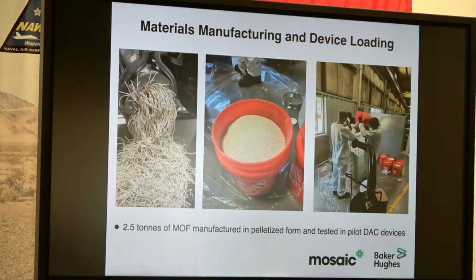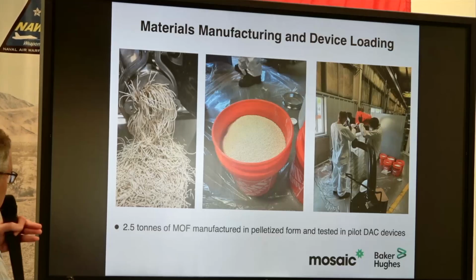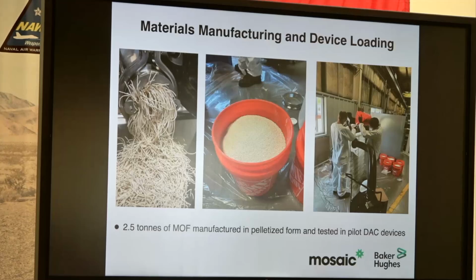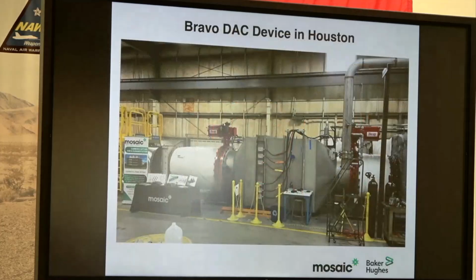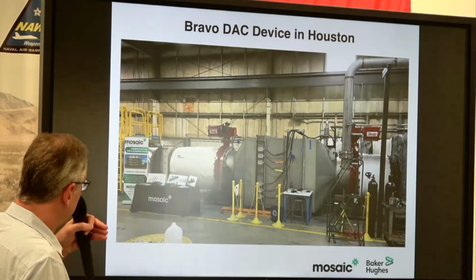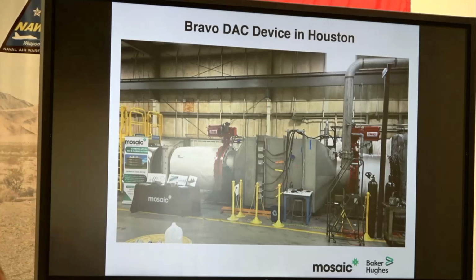But they showed they could make 2.5 tons at a time. And what you're seeing on the left here, that's not spaghetti, that's MOF extrudate. So this extrudate is the precursor to the pelletized form of the MOF, and a lot of technology goes into developing that kind of thing. In the middle is a bucket of MOF pellets, and at the right is a cartridge that holds 50 kilograms of MOF, and 10 of those went into a couple of devices that have been tested now in Houston. So this is, again, capturing CO2 directly from air. Unfortunately, something that we need to do now because of CO2 buildup.